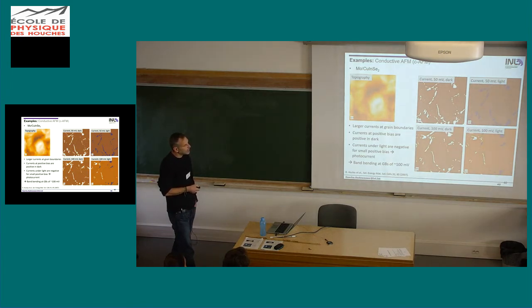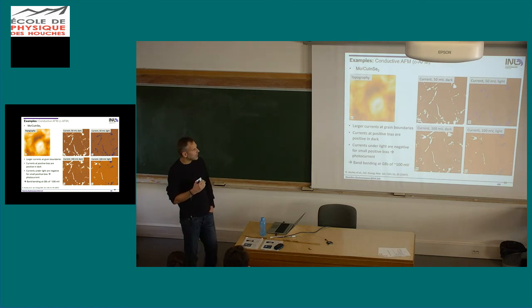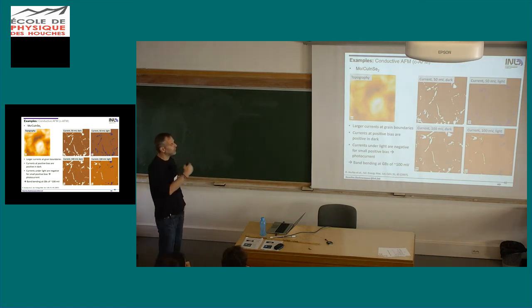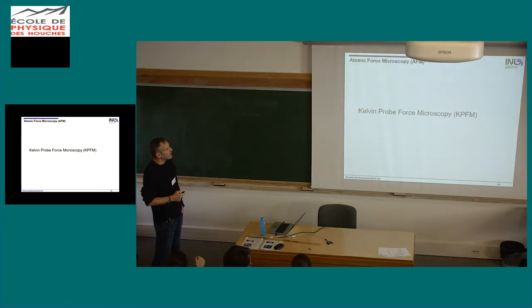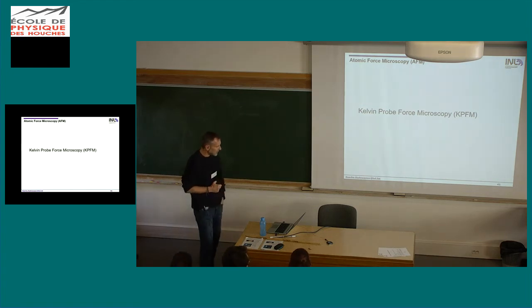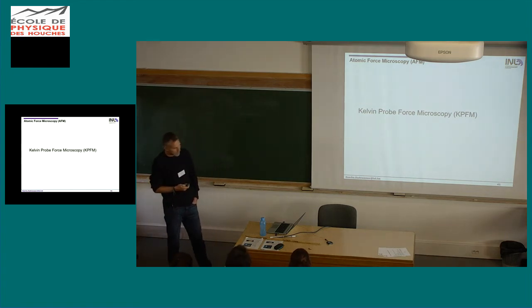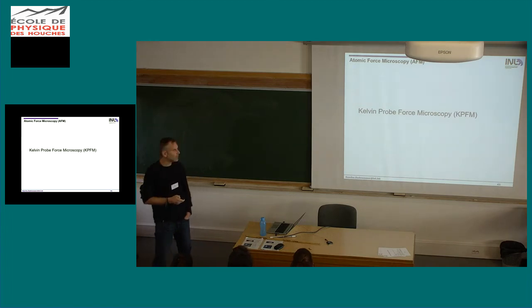However, when they go to a larger voltage, so 100 millivolts, some of them turn white again, so positive again. So what they interpreted is that there's a band bending at the grain boundaries of about 100 millivolts, so that when the voltage is larger than that, then you get positive currents. You're not getting the photocurrents anymore, dominating, of course. So one of the methods that has been most used is Kelvin probe force microscopy, and this is also what we do in Braga and what I did before in Berlin.